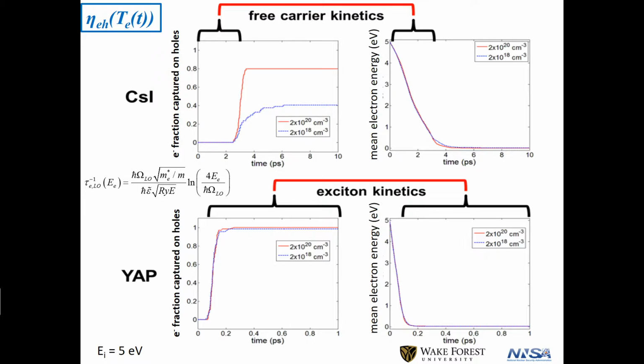so they're not going to form excitons. This is yttrium aluminum perovskite. Perovskites are everywhere these days. This one's heavy, but it has enough light ions in there that it's got a really fast phonon cooling rate, and it's also got a more complicated phonon structure, and that also accelerates the cooling rate. These look like they're not much different, but I expanded the scale 10 times, so this is like 30 times faster than that.